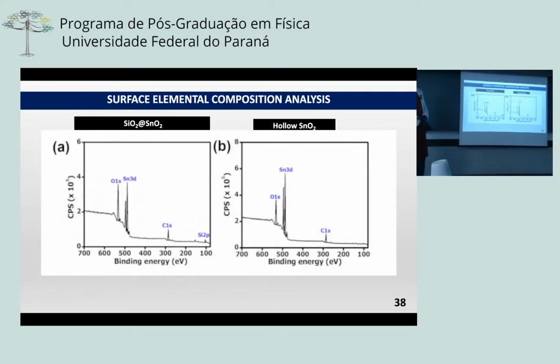And also to determine the surface, to be sure that indeed we removed all the silica. We did X-ray photoelectron spectroscopy, and from this you can see for the SiO2@SnO2 we have oxygen, tin, carbon, and silicon, and for the other one we have no silicon, and the carbon is a result of the carbon tape used during the analysis.